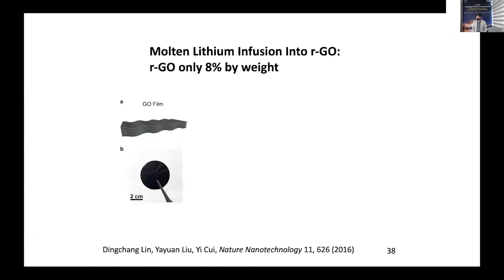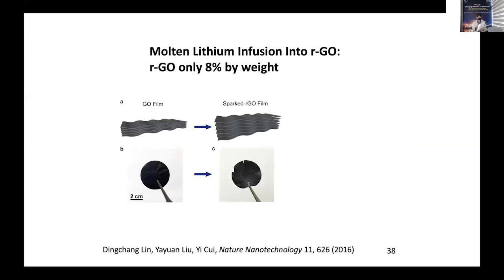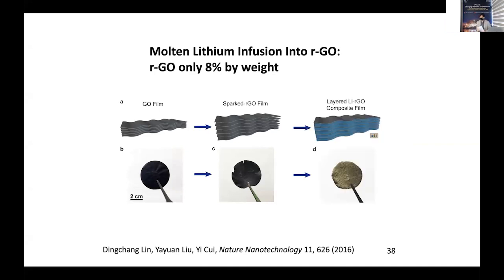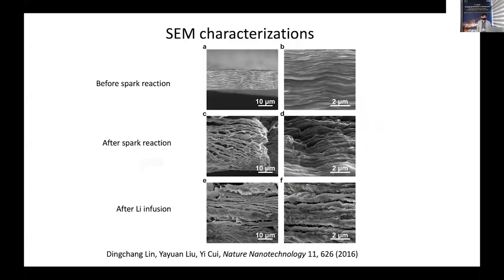So this graphene oxide made by filtration, put into molten lithium, you will see a spark reaction happening, opening up the gap to tens of nanometers to hundreds of nanometers. Lithium metal is embedded into the graphene oxide through the capillary force. If you look at the cross section, before the spark reaction on the top, and then after spark reaction, the gap opening in the middle, after lithium infusion, it looks very nicely embedded, hosted between the graphene oxide.